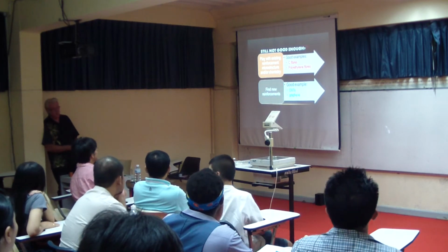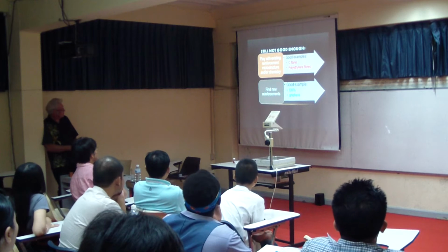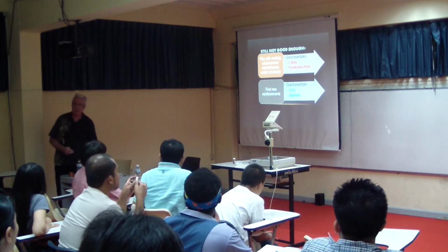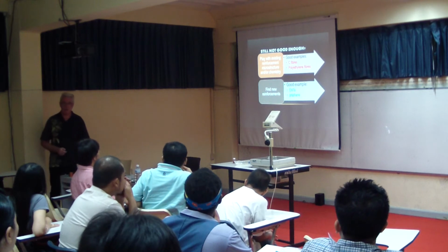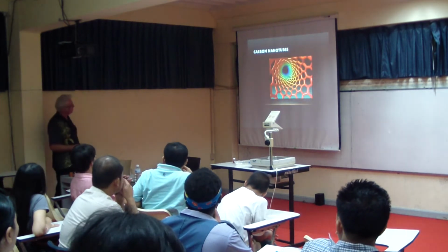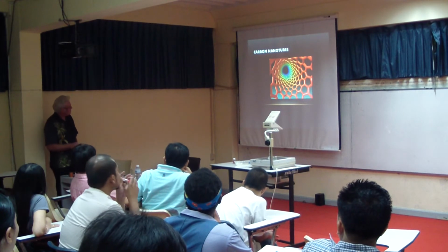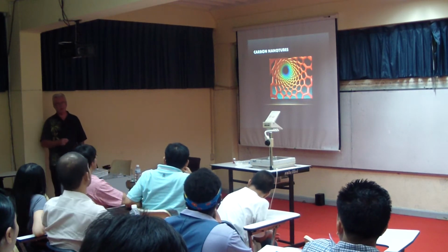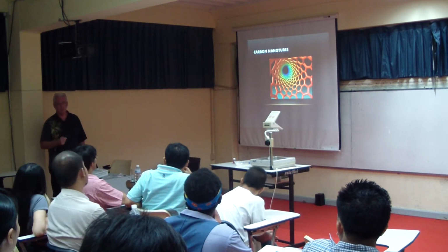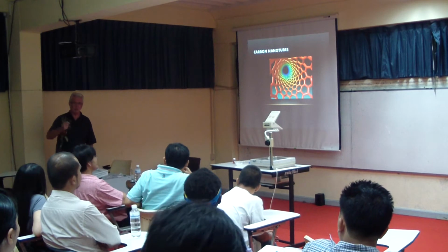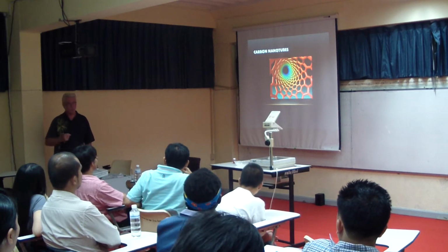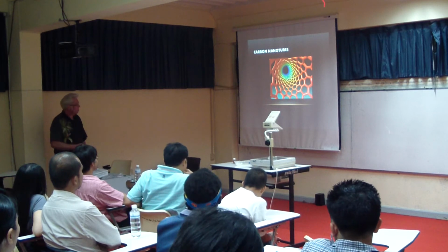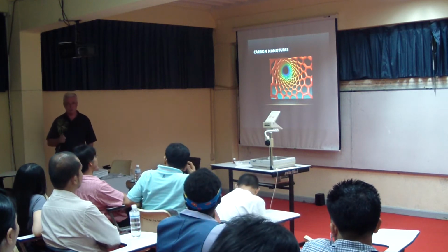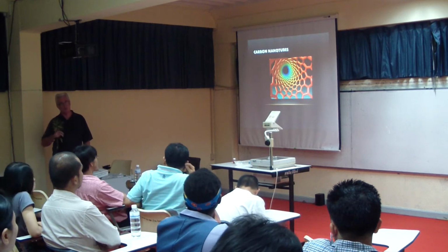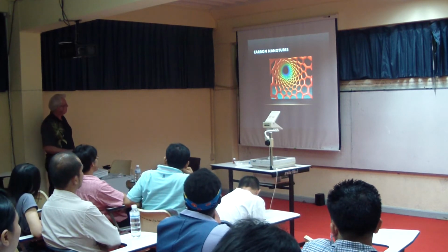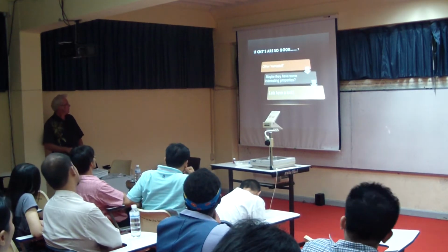Generally, we can use carbon fibres and all sorts of things. But if that's not good enough, we find new reinforcements, and this is where we go to carbon nanotubes and graphene and nanoparticles, because they've got these really nice properties that we want to use. So if we use carbon nanotubes, we can put them in the material. And I say we can put these things in, but it's not easy. Trying to disperse nanoparticles in anything is not an easy task. If you're trying to put them in polymers, you've got to do a lot of surface chemistry in order to get them to disperse evenly. So it becomes a problem.